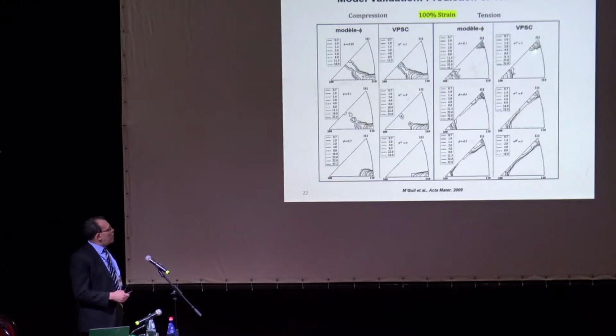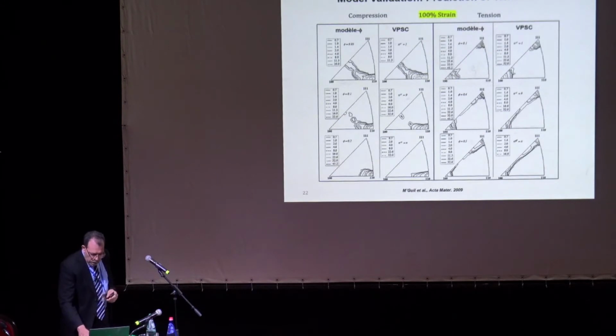But if we take the secant modulus, and we compare it to a small phi, which is close to the upper bound, we get exactly two components, but we don't get this distribution in between. But this is not a big difference. It all depends how much concentration we have here. But usually the concentration of 111 and 100 is the strongest. So we cannot say much, but the compression tells us much better than the tension in this case, or at least it gives us more details about the prediction in texture.